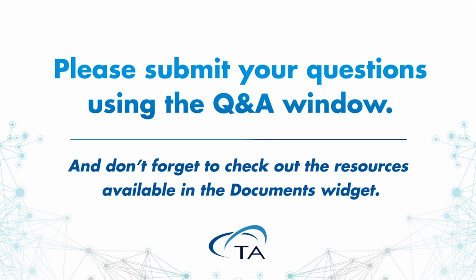Okay, very good. Here's a question about zero shear viscosity. Would you use zero shear viscosity to predict adhesive performance? And if so, what characteristics of the adhesive performance would you predict using the zero shear viscosity? Zero shear viscosity is commonly used. First of all, how do we measure zero shear viscosity, right? Zero shear viscosity can be obtained through a viscosity measurement from low shear rate up to a medium or high shear, right? After you finish the test, you can extrapolate your viscosity curve down to really, really low shear and eventually get to shear rate equals 0.